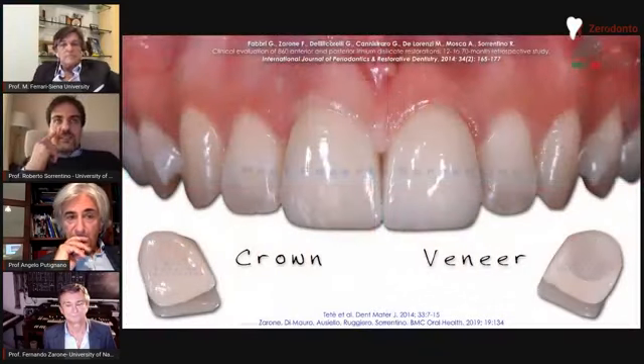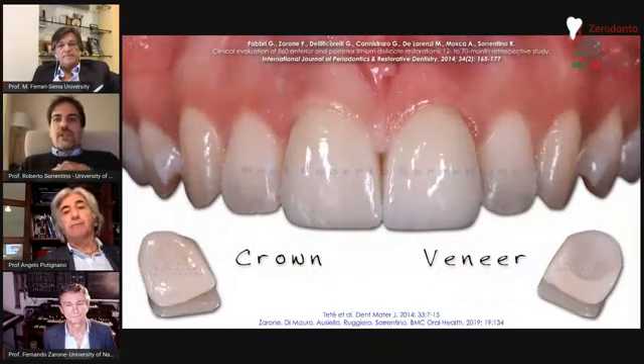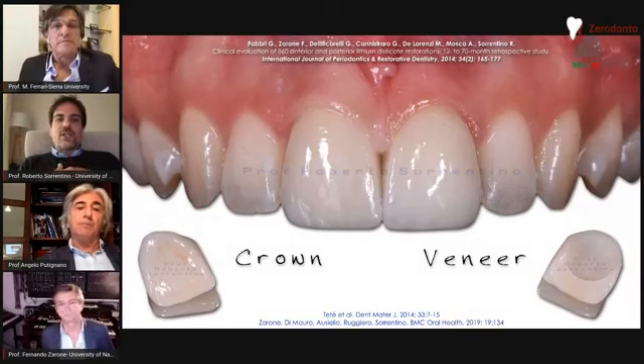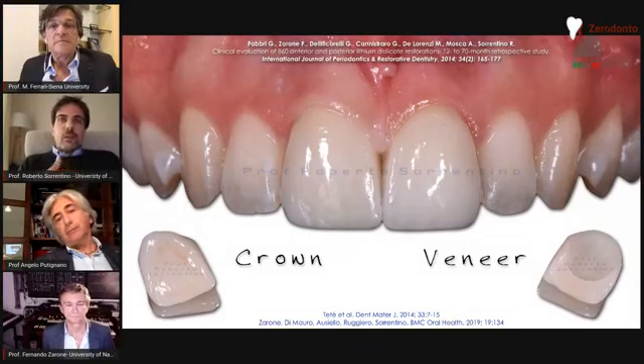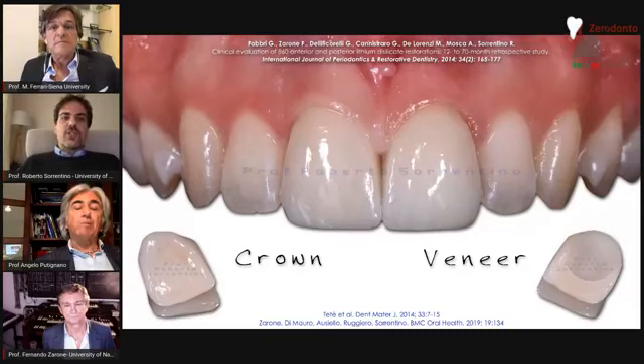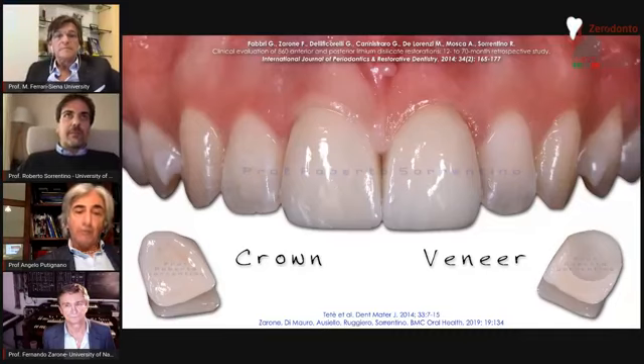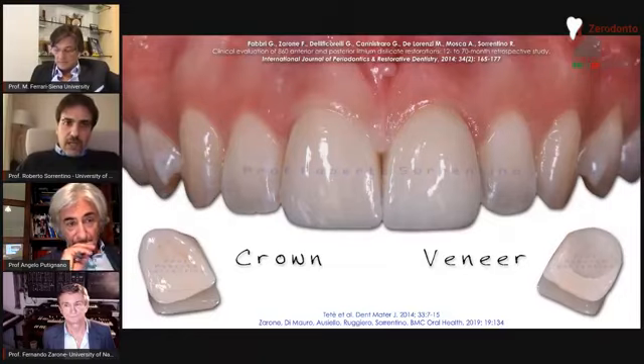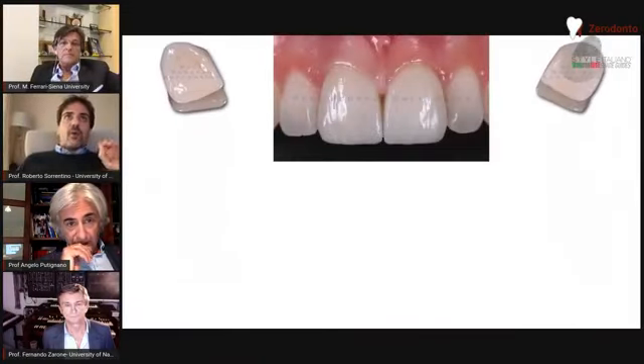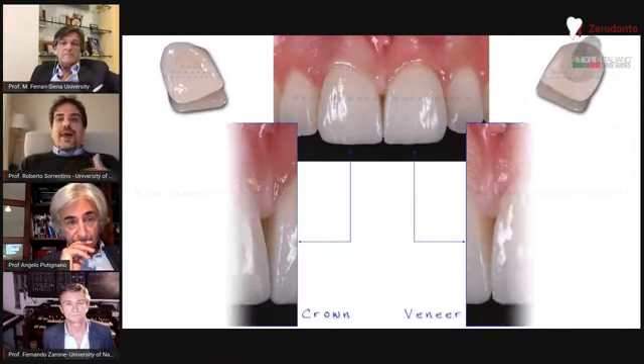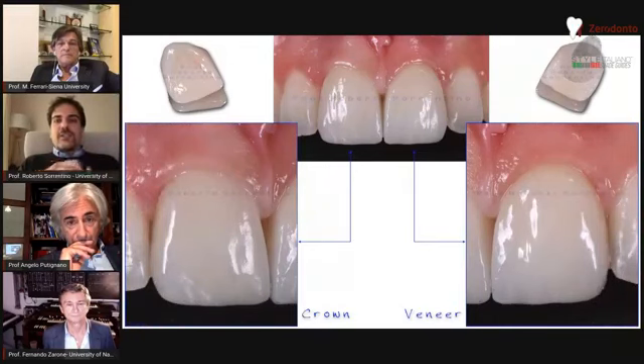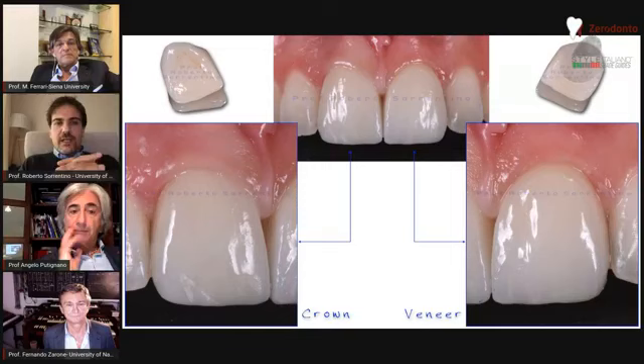Waiting for a couple of weeks, the aesthetic and biologic integration of the lithium disilicate restorations was satisfactory, with the natural tooth-like appearance of the prosthesis and complete healing of the gingivas, as we have reported in these publications. For this purpose, I always ask the dental lab to leave unglazed the margins of the lithium disilicate restorations, as its biocompatibility has been proven by several studies and by our research group as well.